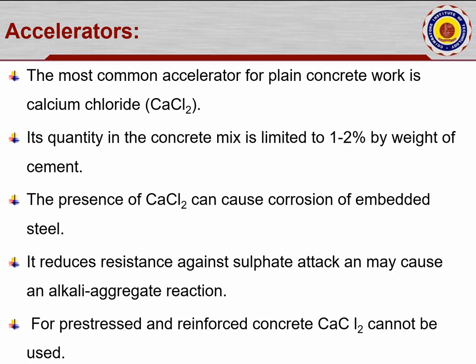The most common accelerator for plain concrete work is calcium chloride. Its quantity in the concrete mix is limited to 1 to 2 percent by weight of cement. Accelerator packaging — whether powder or liquid — will indicate how much quantity to use per 100 kg or per bag of cement. The presence of calcium chloride can cause corrosion of embedded steel, which is a disadvantage.